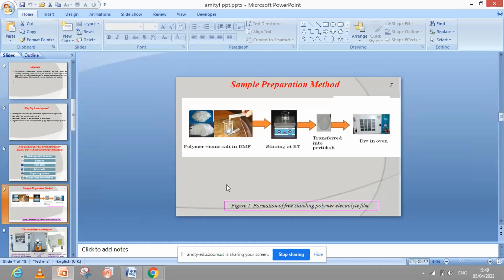Yes, sir. I have measured the thickness using a micrometer screw gauge. What was the thickness? Nearly 150 micrometer. And how did you make sure that your film has a uniform thickness throughout, not different? Because usually, if you have not taken any other measures to make it completely flat, it is very difficult to get a uniform thickness film using a petri dish. So have you done anything for that?